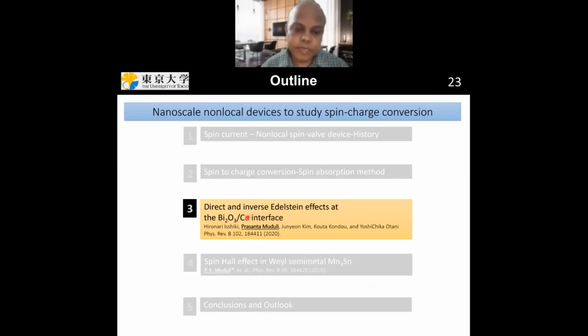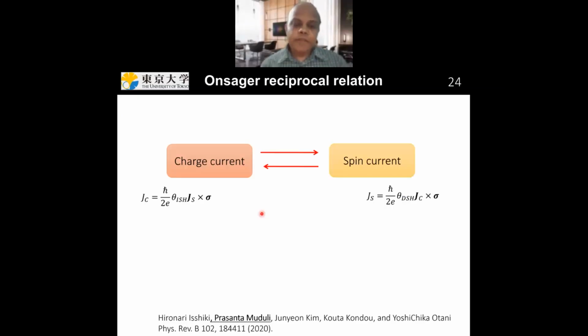So let me give one example of how you can use this method to study spin charge conversion and the Rashba-Edelstein effect in the bismuth oxide and copper interface. So there is also another motivation for this kind of experiment. There is a fundamental problem in the understanding of the Rashba-Edelstein effect. One of the major problems is that in the spin Hall effect, we convert charge current to spin current and spin current to charge current, and you get these two spin Hall angles. And spin Hall angles are dimensionless. So it is not very difficult to assume that the spin Hall angle determined by the direct spin Hall effect and the inverse spin Hall effect will be equal.